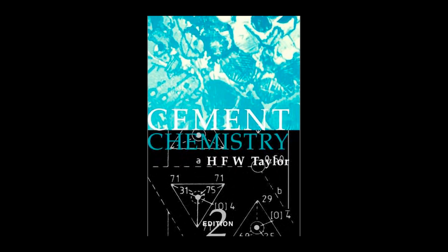periclase, poorly crystalline belite, ferrite, and often a highly reactive calcium aluminate, C12A7, if there's enough alumina present. It's important to note that the less basic phases, like CA or CA2, are typically absent at this stage, which tells you the system is successfully driving toward the desired calcium-rich final phases.